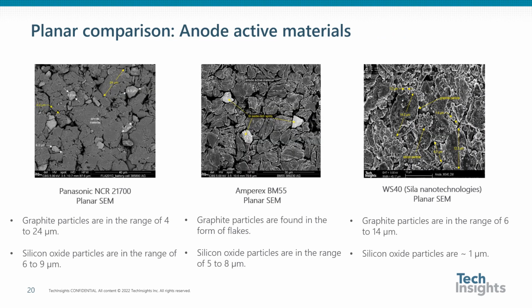These same images show the planar view of the anode. Based on these images, we can say that the content of the silicon-based particles in BM55 cell is lower than NCR21700. They also show that in BM55, both graphite and silicon are smaller compared to NCR21700. To have further details on the source of the graphite, XRD analysis and Raman spectroscopy are required.